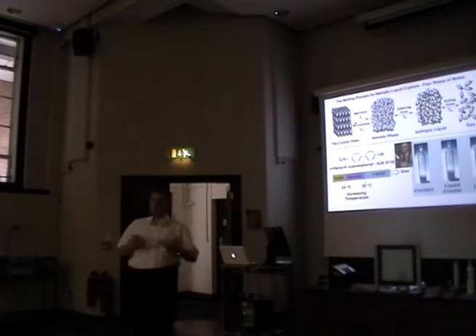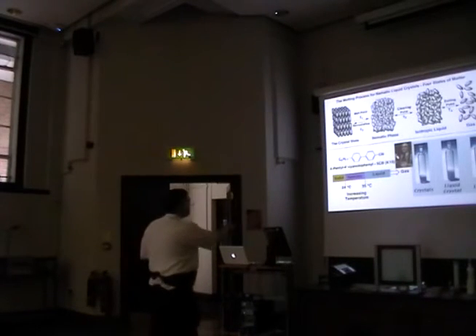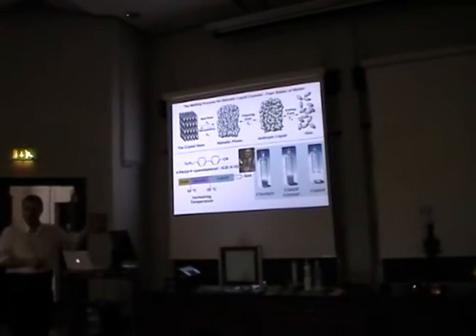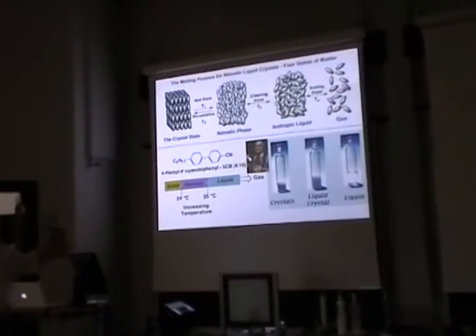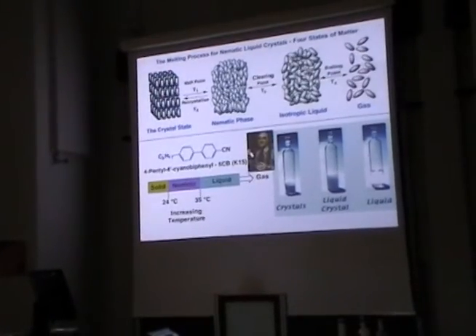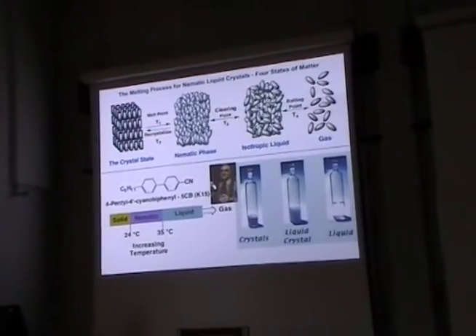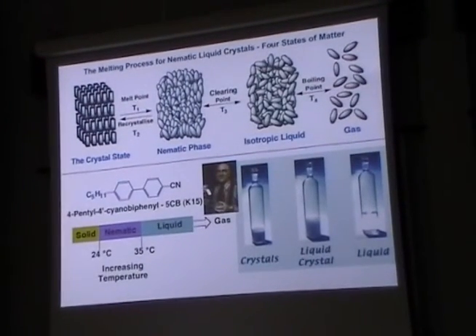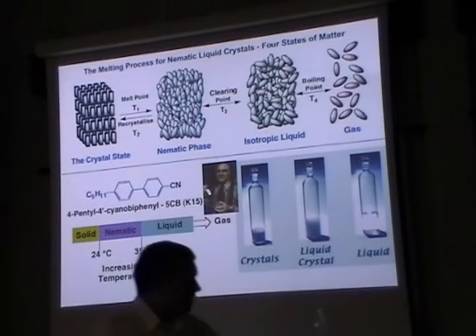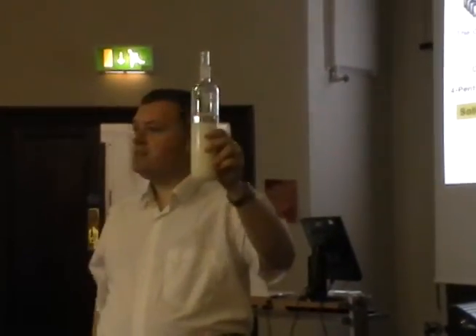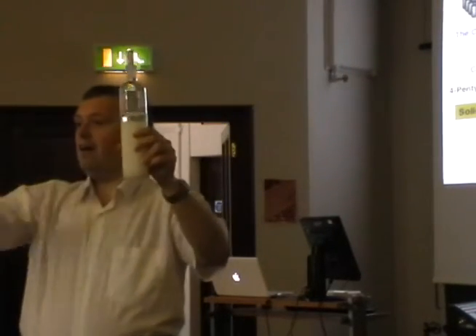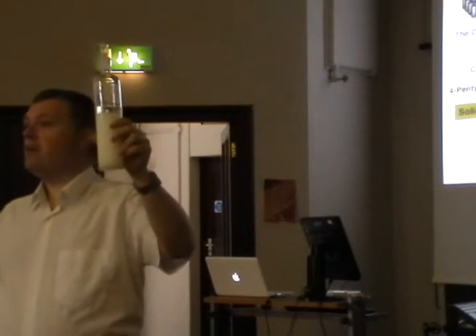It was a room temperature nematic crystal, and it was photochemically stable, and it was electrochemically stable. And so this was the first material that enabled us to have stable materials going into devices. So this went into the early watches and calculators. It melts at around 24 degrees, is nematic through to 35 degrees. So in this bottle, we've got a very good temperature gauge. So this line between our nematic and our isotropic liquid, I know that anything above that is above 35 degrees. At that line is exactly 35 degrees, and below it is below that temperature.